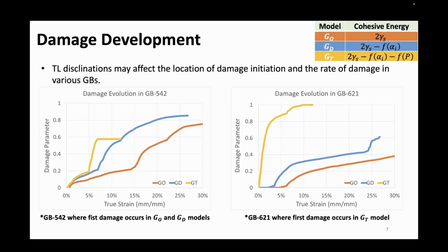When we look at this plot, which shows the damage evolution in different grain boundaries, the GT model starts quite early, at the very beginning of the simulation, and quickly develops to the value of 1, which means that boundary has cracked. So from these two plots, we can confirm that the triple line disclination plays a role in the crack initiation point and the propagation rate.